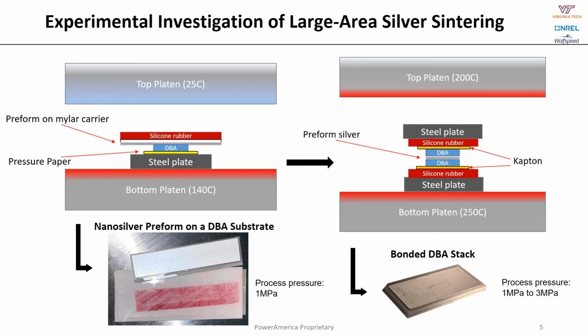As you can see from the diagrams below, when we're working with a nanosilver preform, it's first deposited on the substrate using a process step at 1 megapascal and then sintered for 60 to 90 seconds using a pressure range to determine where the optimal pressure is for silver sintering, between 1 megapascal and 3 megapascals. And this process is being compared to a very similar process using a screen-printed nanosilver paste.